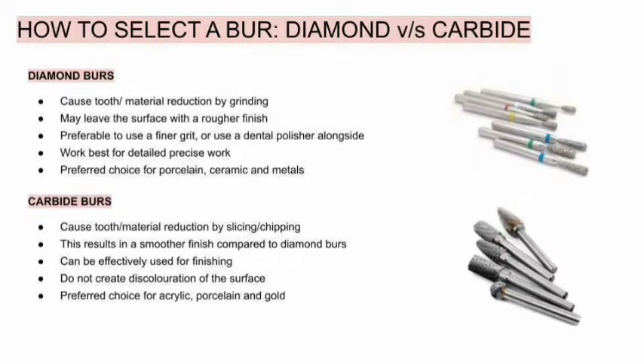Now, what are the main differences between diamond and carbide burrs and how can one select the best burr for one's needs? So, diamond burrs cause reduction of the tooth or of the material by grinding, whereas carbide burrs have the same action through slicing or chipping. Thus, diamond burrs may leave the surface that they are grinding with a rougher finish, while carbide burrs result in a smoother finish compared to diamond burrs. Therefore, it is more preferable to use a finer grit for diamond burrs or use a dental polisher after using a diamond burr, while carbide burrs can be effectively used for finishing.